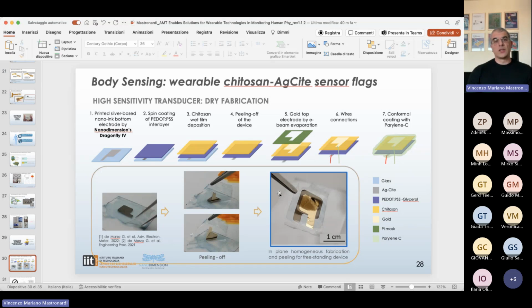So the first step of this fabrication includes the deposition of the bottom electrodes by exploiting the Nano Dimension Dragonfly 4. Then we deposit on the printed electrodes a coating of PEDOT:PSS interlayer that acts as an adhesion promoter for the chitosan to the silver electrode. It is a conductive material. Before peeling off the device from the glass substrate, we deposit the top gold electrode by exploiting e-beam evaporation, before achieving the wires and the connections to the final sensor that is shown in this picture.